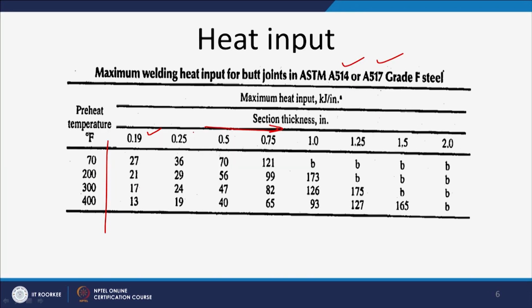Well, there is another set of the steels in the Q&T category where the more drop in the yield strength takes place. So, in that case yield strength of the weld joint is taken as a qualifying criteria for deciding or for determining the preheat temperature, heat input, as well as for a given thickness of the plate of the given steel.